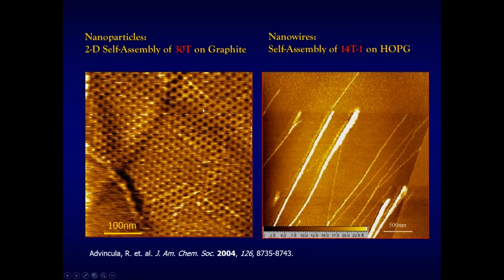Using a tributyltin initiator, we can then couple this to react with another dibromothiophene to produce 7T, and then repeat this process with dibromothiophene to grow 15T. So easily we can see here first generation, second generation, third generation of dendrons, which we can then assemble into larger dendrimers as such. So if we take, let's say, this tetrafunctional bromo derivative, we can then couple three thiophenes to produce this 14T derivative, or we can take the 7T to come up with this 30T derivative.